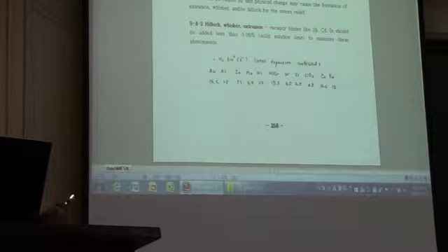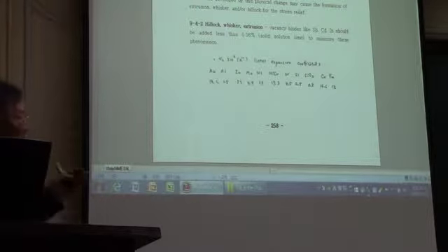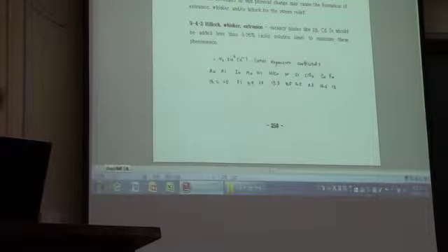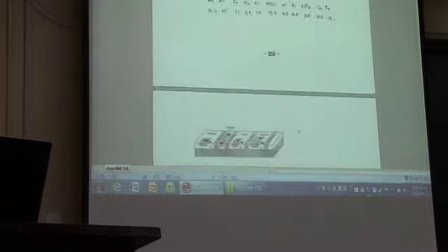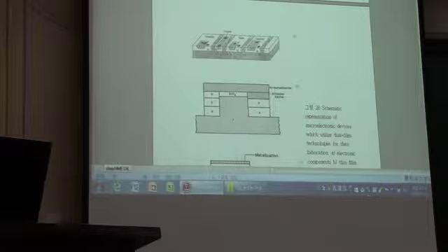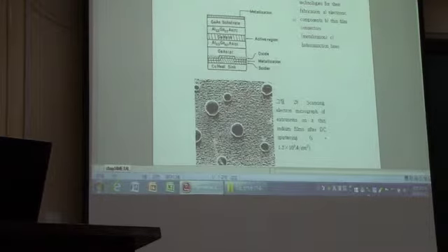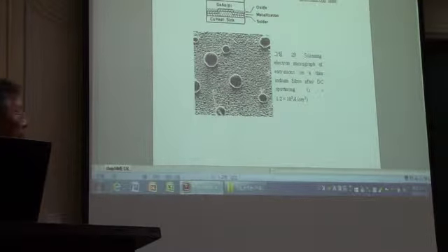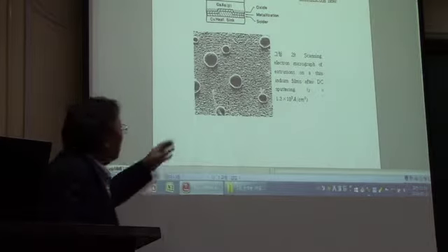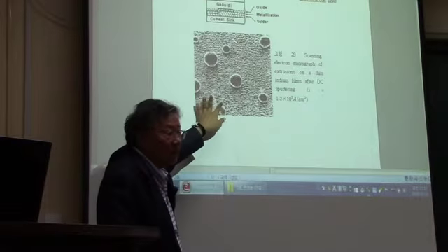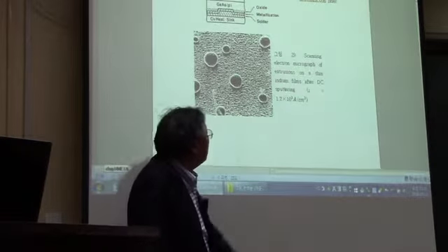stress. And this mechanical stress will lead to abnormally fast growth of a single crystal, and that is going to be called a whisker. Okay? And sometimes we are going to see some kind of hillocks on top of the film.